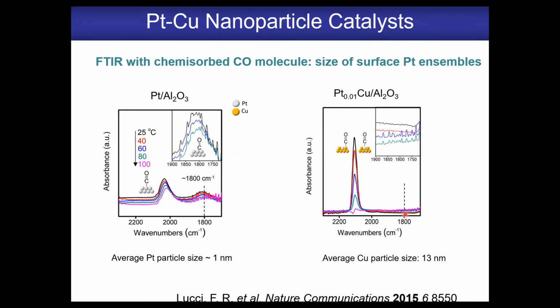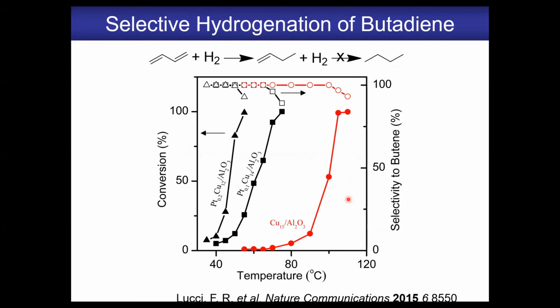We don't see any bridge bound CO. So at the surface, what we have is single platinum atoms in the copper surface. And then for running a reaction, we tried again the thing we had done in ultra high vacuum, butadiene hydrogenation. What you see is on a pure copper nanoparticle catalyst, the light off doesn't happen until about 100 Celsius, whereas just putting 1% platinum atoms into that copper nanoparticle drops that light off temperature by 50 Celsius.